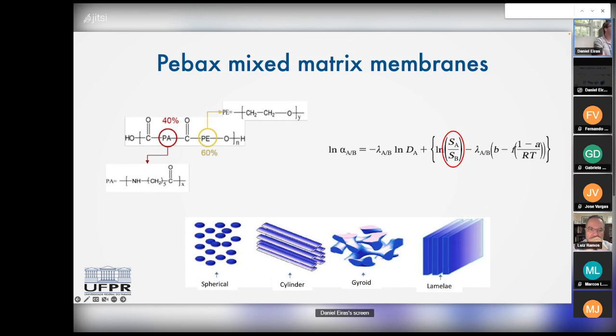So the advantage of this material is that the PEO group has great interaction with CO2. So it basically increases the term S_A/S_B in the equation of the selectivity. So this material has a very high selectivity for CO2 over methane and CO2 over nitrogen. So it can be applied for biogas or natural gas separation and carbon capture.